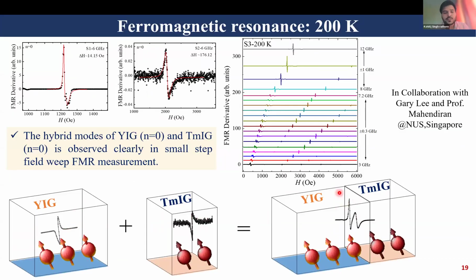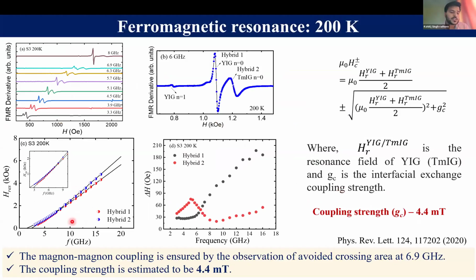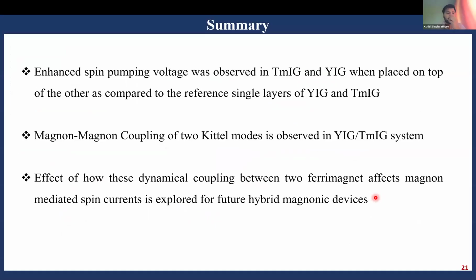On analyzing this hybrid mode in this broad frequency region, we found that around 6.9 gigahertz there is a signature of an avoided crossing region. Even this behavior of the hybrid mode, delta H, shows us that damping like torque is mostly contributing towards the coherent spin pumping, resulting in a coupling strength of 4.4 millitesla for this system. So I would like to conclude my talk: enhanced spin pumping voltage was observed for the YIG and TMIG when they were placed on top of each other as compared to the reference single layers. And the magnon coupling was shown for the two Kittel modes of the YIG and TMIG systems. This dynamic coupling would help in preparing hybrid magnetic devices for future applications.